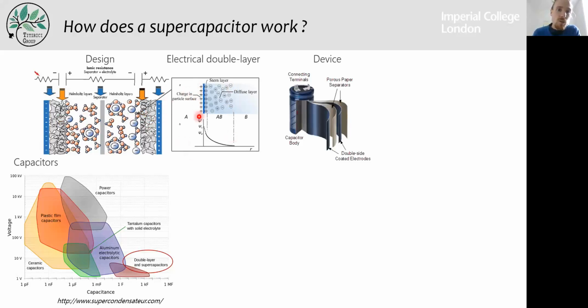This is basically all the charge that is inside your electrode, formed by electrons, that is going to be screened by your electrolyte ions. And since only one monolayer of ions cannot fully screen the charges of your electrode, you will also have a diffuse layer, which is composed of a concentration-dependent layer of ions that is driven towards the surface. And that's how a device looks like. So you have your 2-sided electrodes, where usually your carbon powder is coated on a metal foil, and your porous separator, and you can basically wind up these layers and make a cylindrical device like this.